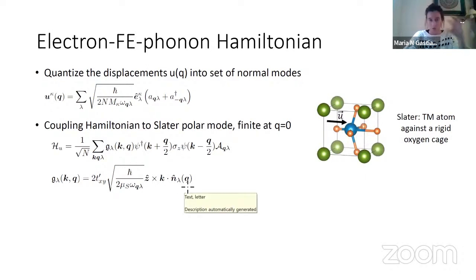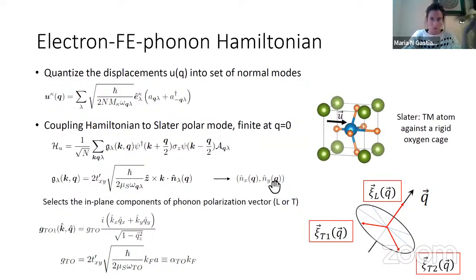And because I was showing you this particular process, this EU component of the coupling will only couple to the EU components of the polarization of your mode, which in this case is going to be in X and in Y. So you can essentially get any lambda normal mode of your system, which can be longitudinal or transverse, and if it breaks inversion in this way, it will have a finite coupling of this form. It will be proportional to this induced hopping matrix element, and of course also proportional to the zero-point motion of that particular mode. This would be the reduced mass and so on. So this is quite the standard form.